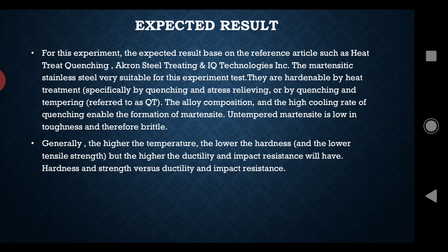and untempered martensite is low in toughness and therefore brittle. So the quenched part is usually very brittle, and it is reheated to a temperature below the critical temperature to temper the part, with a soak period. Generally, the higher the temperature, the lower the hardness, but the higher the ductility and impact resistance. Hardness and strength, ductility and impact resistance are balanced by the heat treaters.